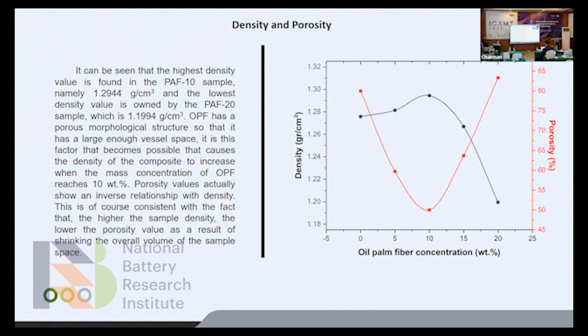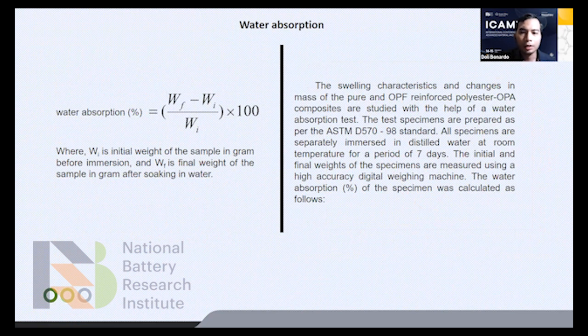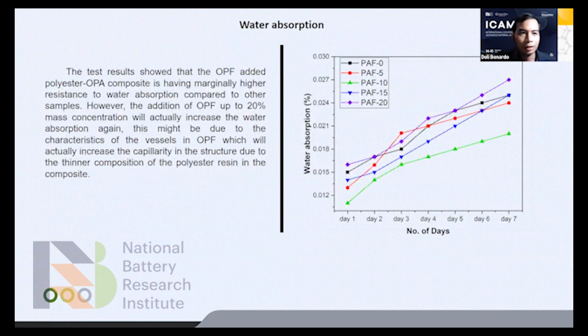Okay. And then the water absorption. The water absorption of the specimen was calculated using the following equation. And the result is that the OPF-added polyester OPA composite has marginally higher resistance to water absorption compared to the other samples. But when the OPF reaches 20 weight percent, it actually increases the water absorption again. This might be due to the characteristic of the vessel in OPF, which will actually increase the capillarity in the structure.